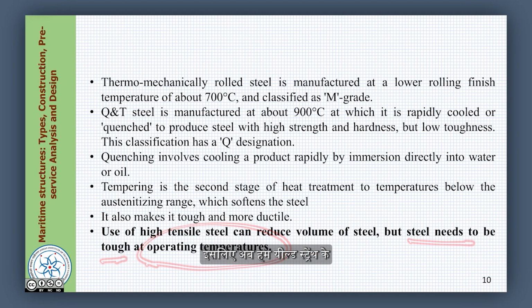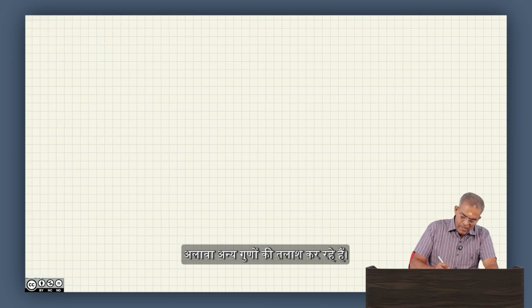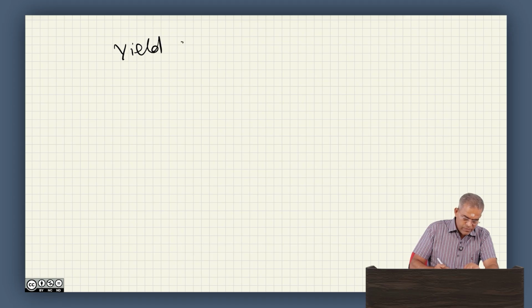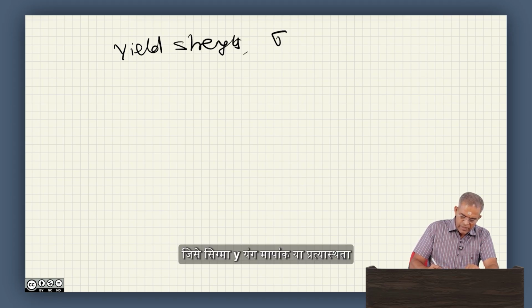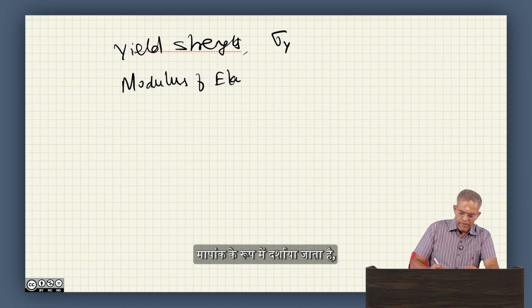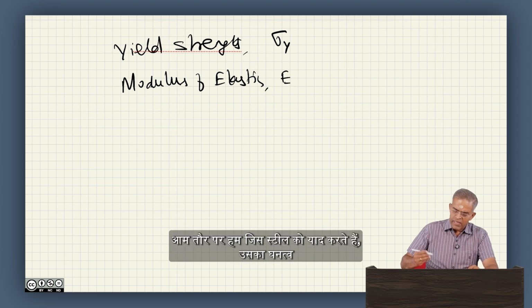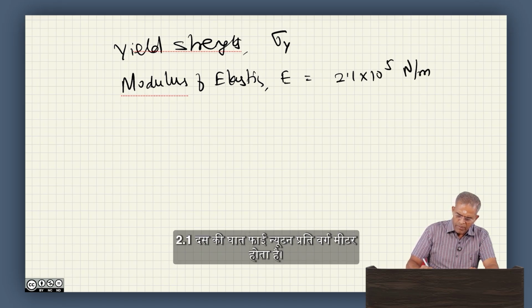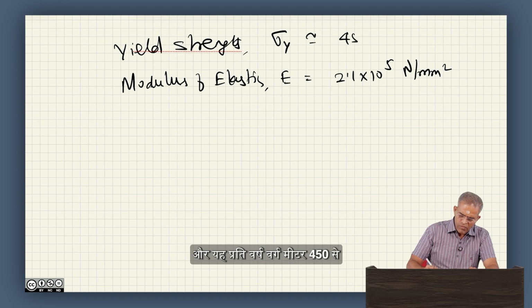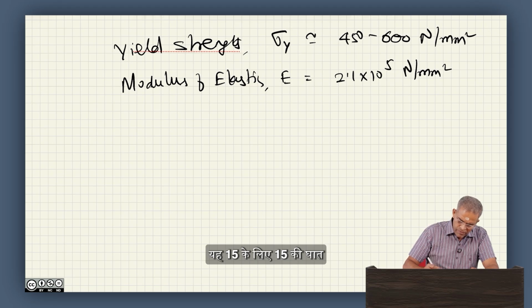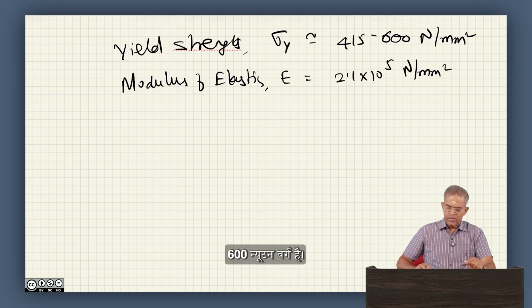So, use of high tensile steel can reduce the volume of steel, no doubt about that, but steel needs to be tough at operating temperatures. So, we are now looking for properties other than yield strength, which is indicated as sigma y, Young's modulus, or I should say modulus of elasticity, which we call E. Generally, the value for steel which we remember is 2.1 × 10^5 Newton per mm square, and yield strength varies anywhere from 415 to 600 Newton per mm square.